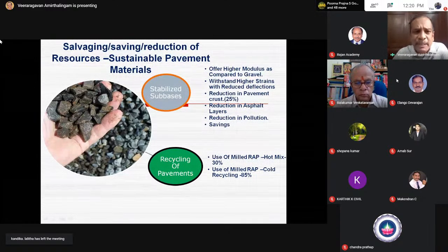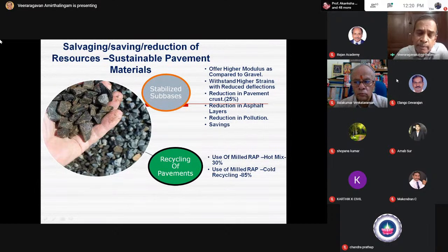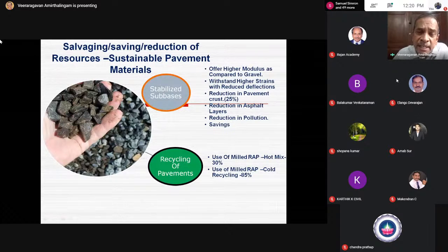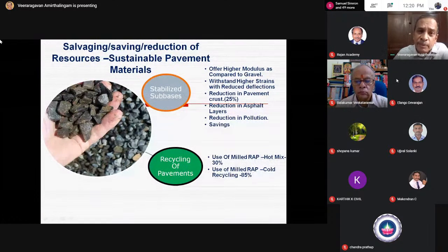You can also recycle the materials, where you can add up to 30% of reclaimed asphalt pavement material, RAP, in a hot mix. You can have up to 85% of RAP in a cold mix. In the Chennai Tada section, 100% of the RAP has been used. It is possible to use entire reclaimed material in pavement design and construction. So the future of India, and not only India, around the world, is salvaging the already constructed pavement, saving the material, reducing the aggregate consumption, and ensuring a satisfactory performance.